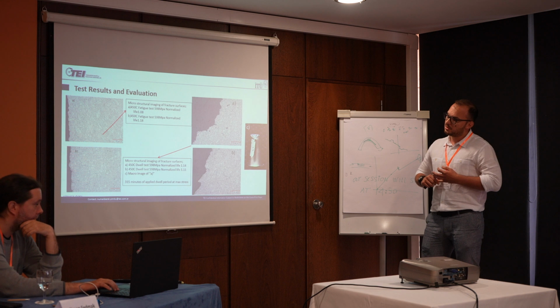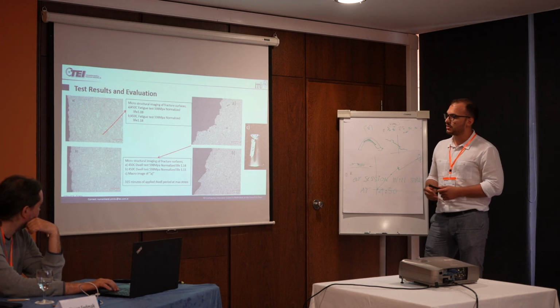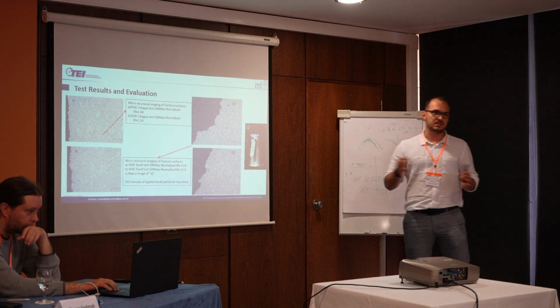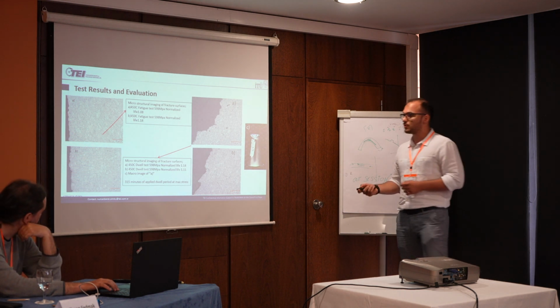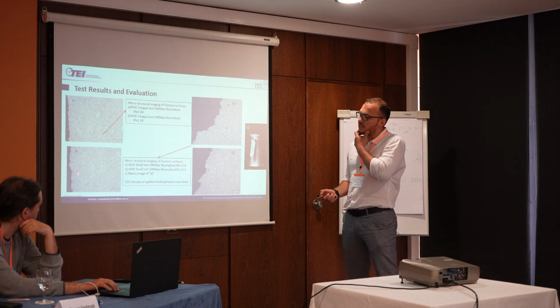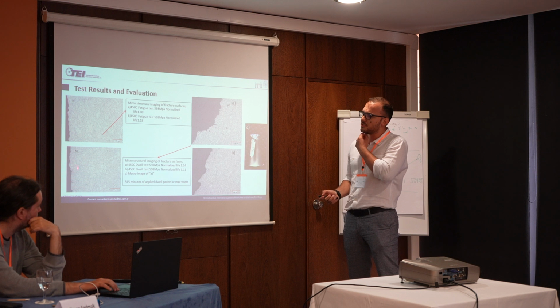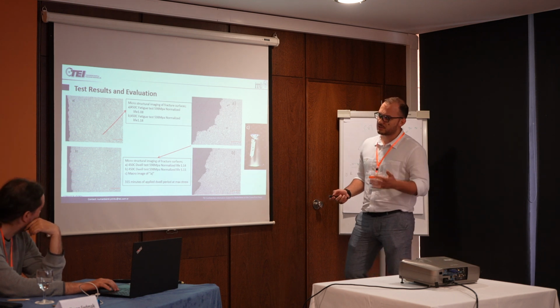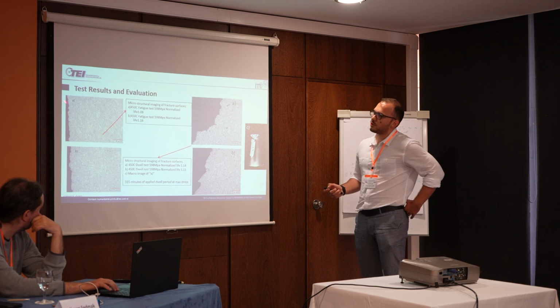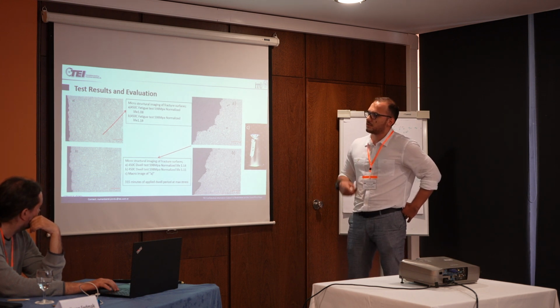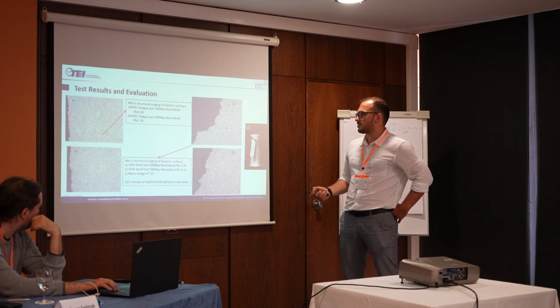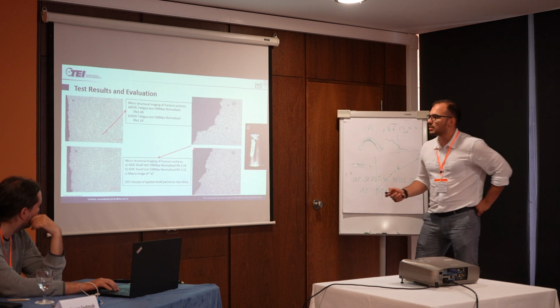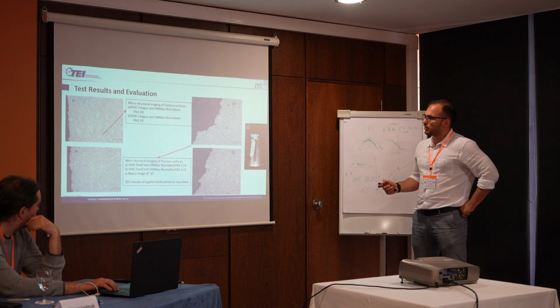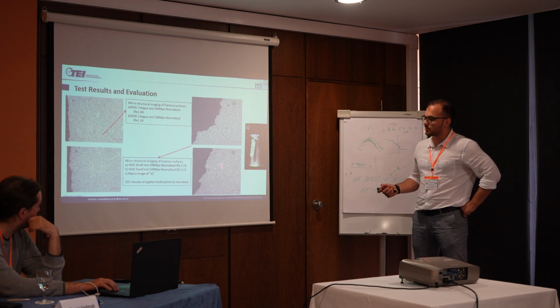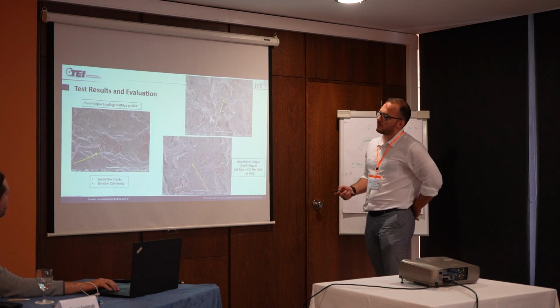So once we saw those results, we actually looked at fracture surfaces and did some SEM monitoring. Here we saw that on the left-hand side we have a specimen fracture surface which was not worked under dwell conditions. We can see that the surface is pretty much smooth, as we expected from standard fatigue tests. But once we applied dwell, you can see in the micro image here that the topography is changing drastically, and we can see it on macro scale too.